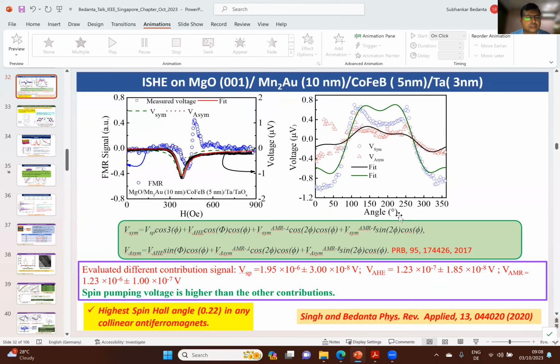Yes, very nice question. Thank you. So, for platinum, of course, as you know, there are widely reported values, and the range is something like 0.02 to maybe 0.3 or so. So I think the value shown here is much stronger than platinum, I would say. And it's much cheaper. But I think the spin to charge conversion is happening very efficiently, and most importantly, because it's an antiferromagnet, it has other repercussions, as I said, like terahertz spectroscopy and so on. So to summarize, this seems better than platinum, I would say.